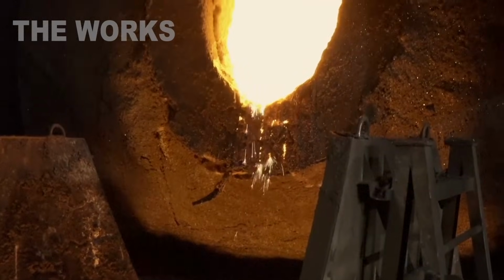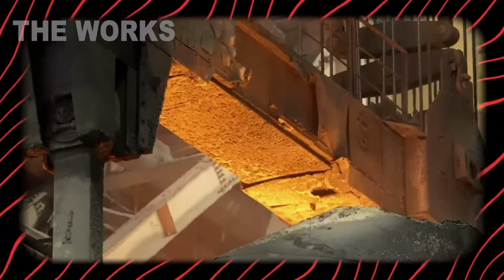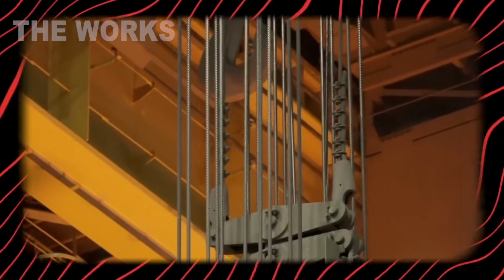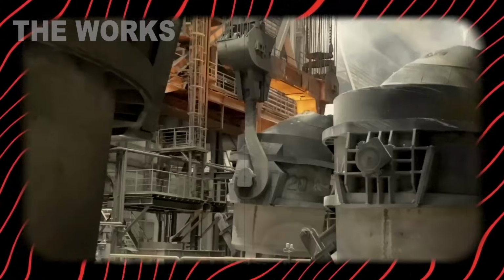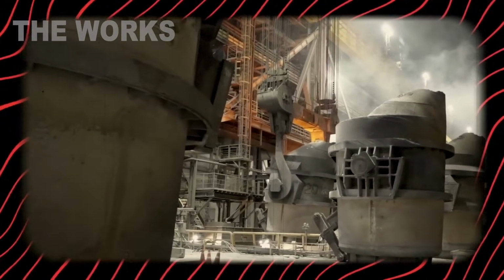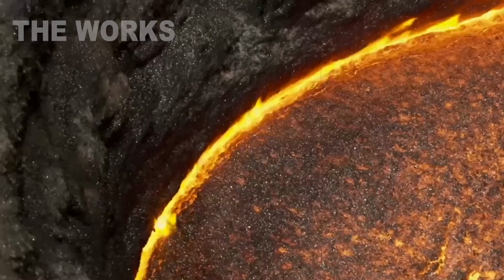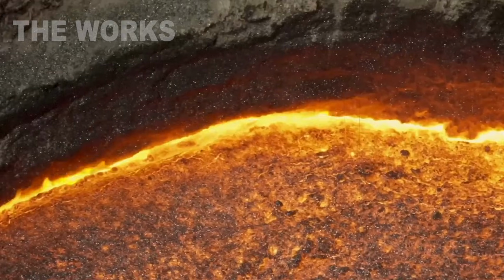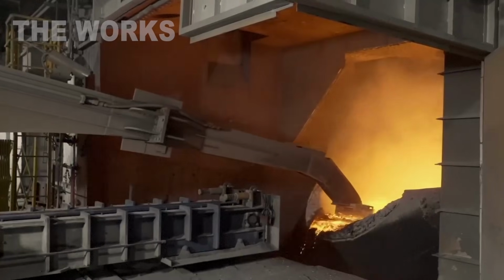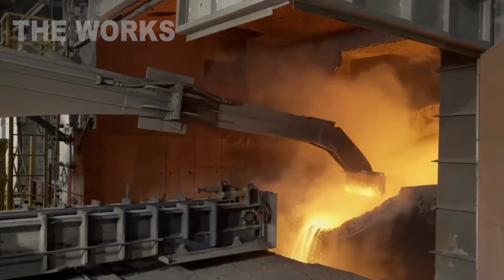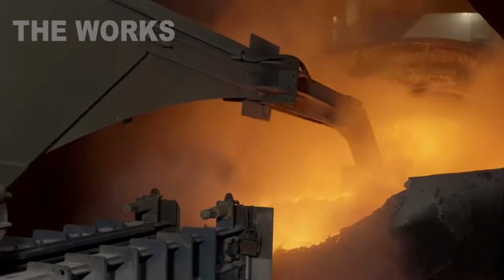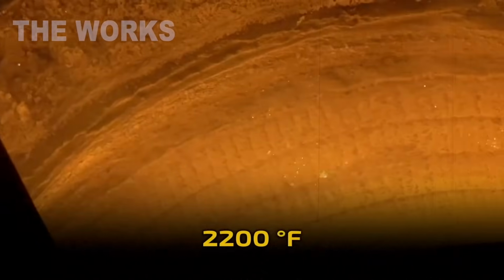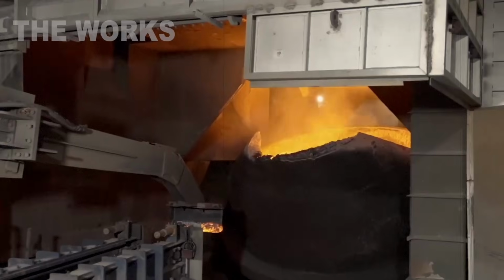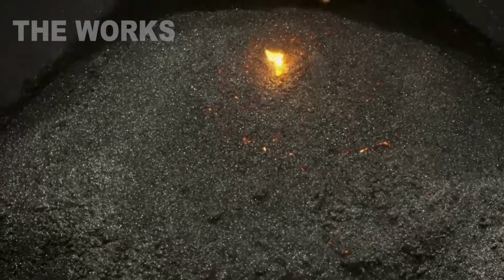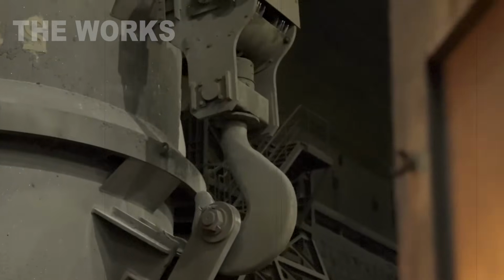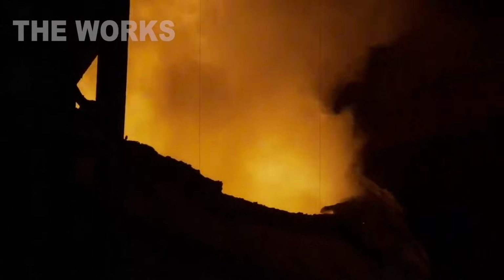The sulfur transforms into sulfur dioxide gas, which is captured and used to produce sulfuric acid, a crucial industrial product. This not only cuts down on air pollution, but also creates an additional valuable product. Next, the zinc oxide is mixed with coal and heated to even higher temperatures, over 2200 degrees Fahrenheit, sometimes even 2700 degrees, depending on the specific furnace technology. At these extreme temperatures, a reduction process occurs. The carbon strips oxygen away from the zinc oxide, freeing up pure metallic zinc.